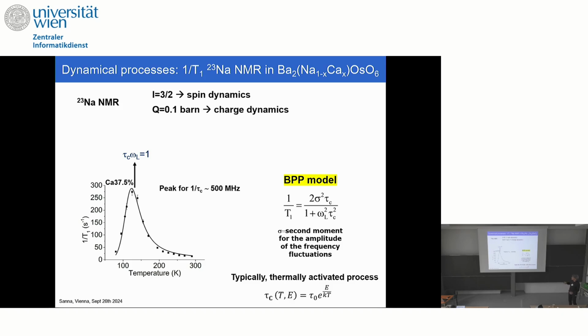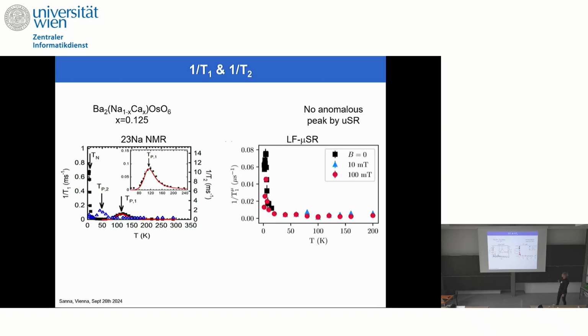And by assuming that there is a thermally activated process, we can determine the energy of the barrier, the activation barrier of this process. We can also measure by the amplitude of this peak the second moment of the amplitude of the perturbing field. And by comparing NMR, here is the NMR peak of the previous page, with µSR, we can see the critical fluctuating peak at the magnetic transition temperature, which is here. Then T1 displays another peak, here is the zoom, which is related to these dynamics.